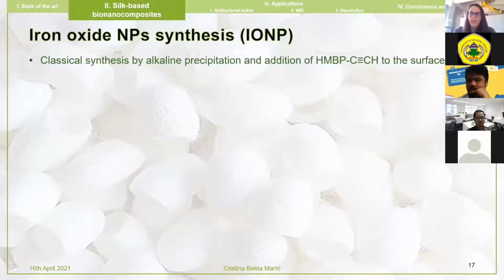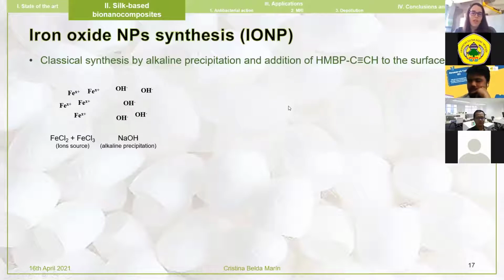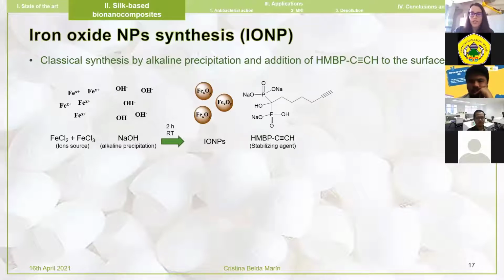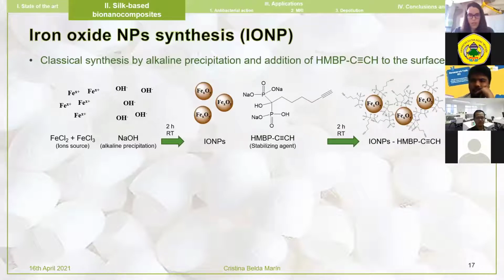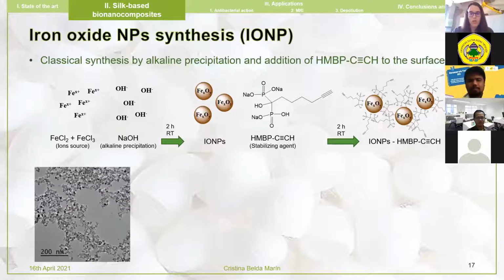Finally, for iron oxide nanoparticles, we synthesized them by the co-precipitation method in presence of an alkali. Then the obtained iron oxide nanoparticles were coated with our stabilizing agent, and then placed into a water solution.